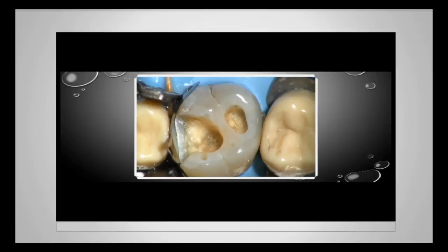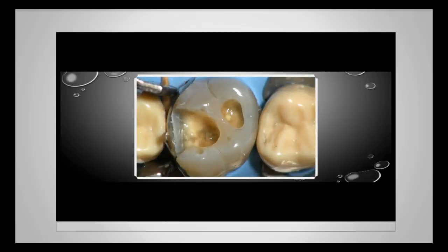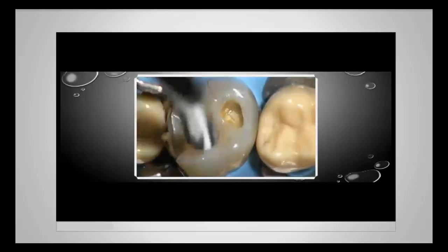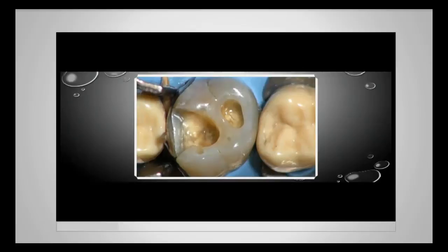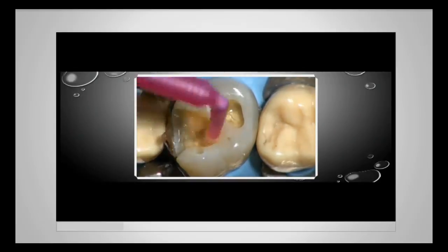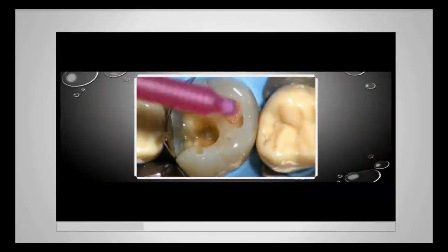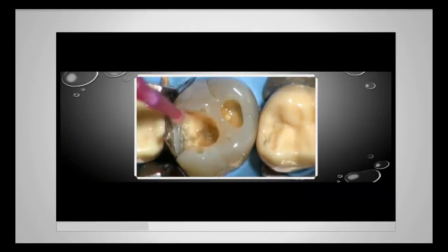Here we come. We've done an etch. We're drying this. We've done an etch prime. Now we're going to come in with the bond. We're going to scrub our bond in, and you're going to notice I soak up some of the bond with a 2x2. So there's a 2x2. I'm going to go in and make sure it's not pooled. Then I'm going to come in and make sure it's smooth. I'll cure that.